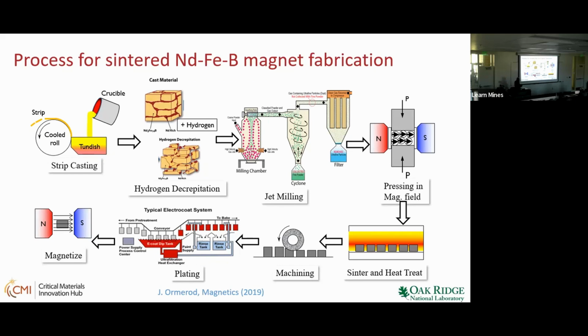And once you do the strip casting, the next step is hydrogen decrepitation. So that's a really good process. You just take a magnet or even this cast material, and with hydrogen, just at room temperature, it will crumble into powder. So that's a good thing. Even if you want to recycle magnets, that's what you would do.